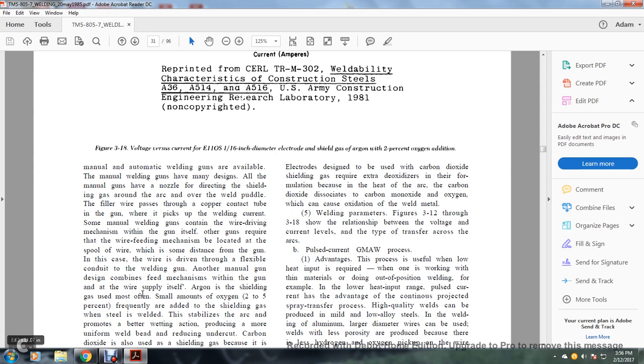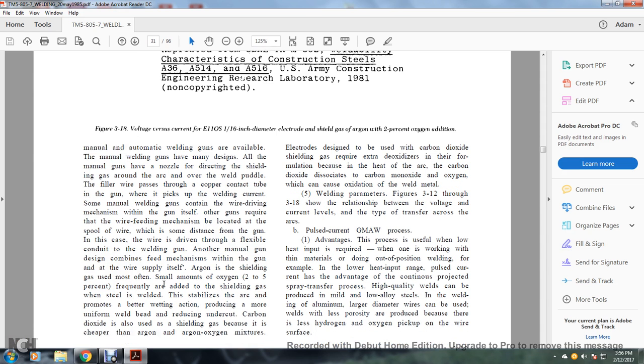Argon is the shielding gas used most often. Small amounts of oxygen, frequently 2 to 5%, are added. The shielding gas stabilizes the arc and provides better wetting action, producing a more uniform weld bead and reducing undercut. Carbon dioxide is also used as shielding gas because it is cheaper than argon and argon-oxygen mixtures. The electrode designed for carbon dioxide shield gas requires extra deoxidizer in the formulation, because the heat of the arc dissociates the carbon dioxide into carbon monoxide and oxygen, which causes oxidation of the weld metal.